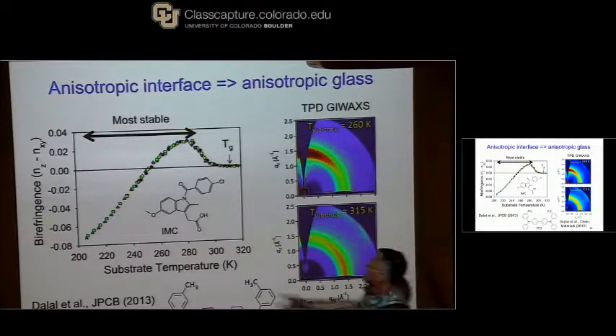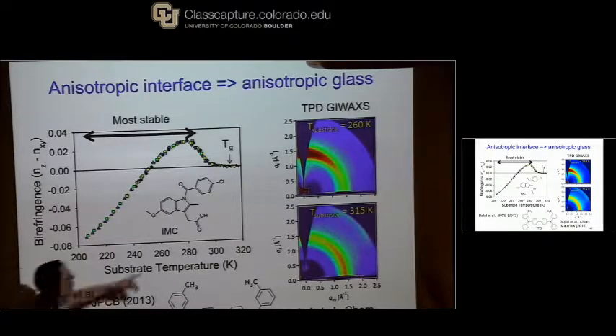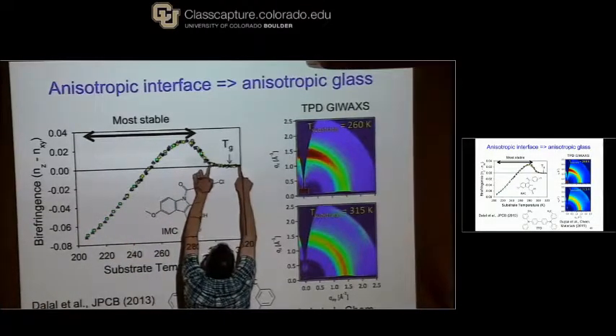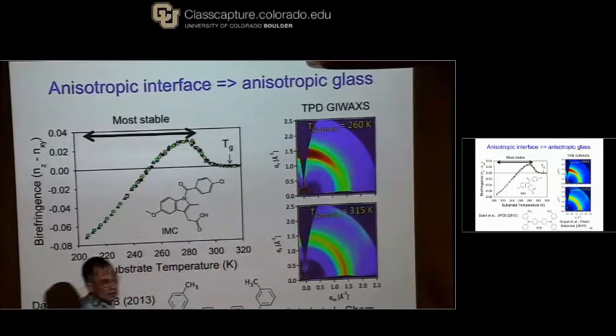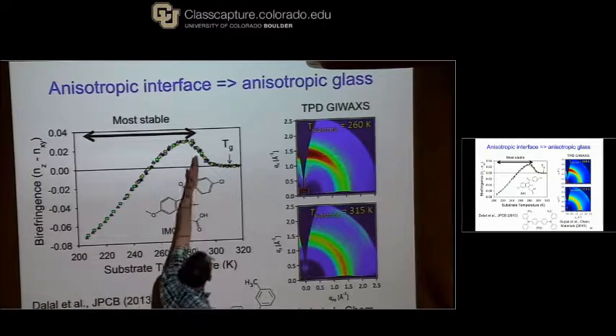Okay? So this is indomethacin. All right? This is a very simple measure of anisotropy. You get it from those ellipsometry experiments. It's the birefringence. It's the difference in the index of refraction for light, if this is the film, for light that's polarized like this and light that's polarized like this. Okay? So there's a temperature range when we vapor deposit down below TG, where we're making, by this measure, isotropic materials. And then below that, we make anisotropic materials. Okay? Yes? Where is the thermodynamic control regime? Excellent point. It goes to about right there.